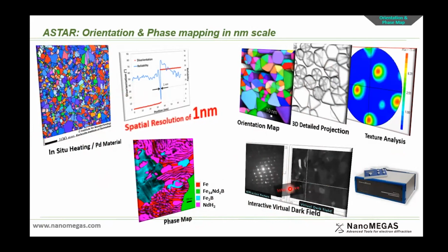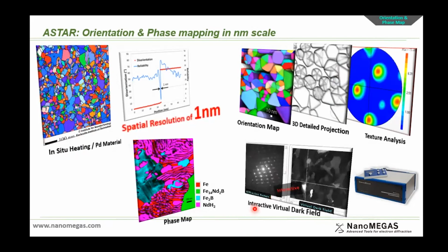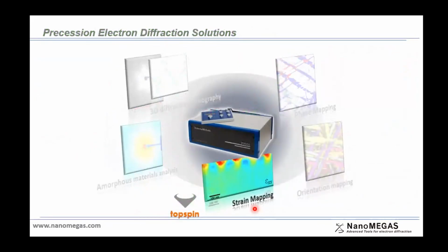Okay, strain mapping uses again the 4D SPED method for data acquisition. The previous application that I told you, the orientation and phase mapping, is using a kind of template matching. In this case, for the strain analysis, we need to compare all the series of diffraction patterns that have been collected with a diffraction pattern that is coming from a known strain area. So in this case, we need to have a single crystal and all our data to be collected from a single crystal that would be zone oriented, and then compare the series of diffraction patterns with a reference pattern. What we obtain at the end is strain maps like this in the X and Y direction.